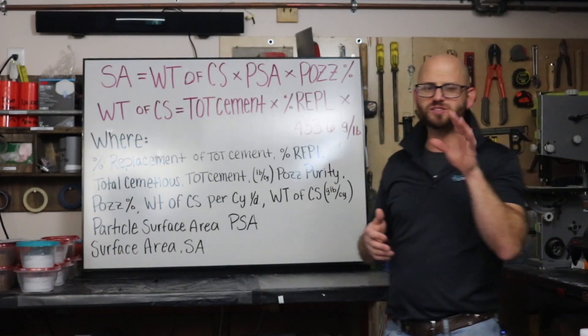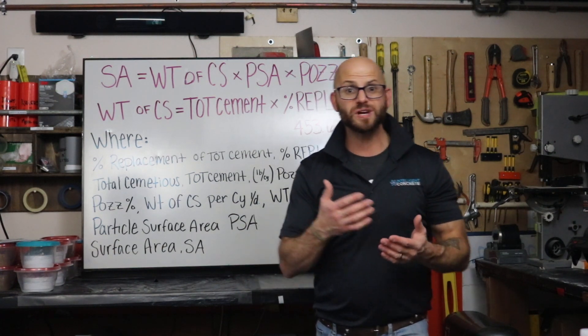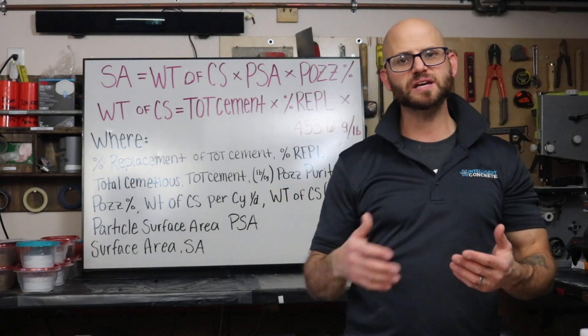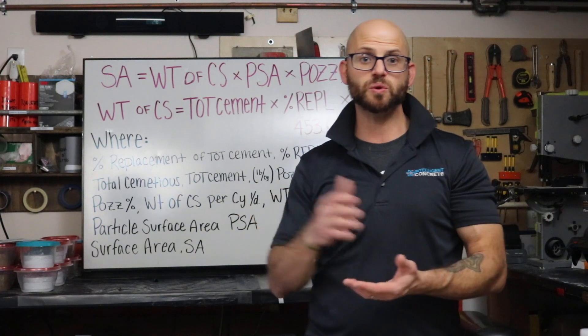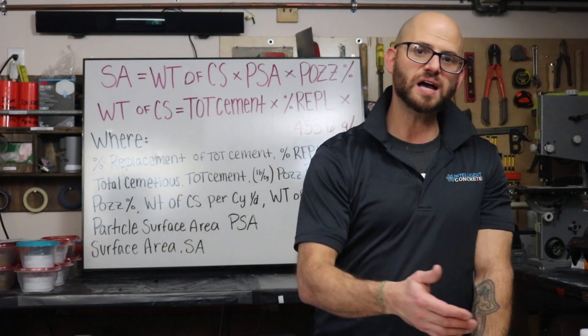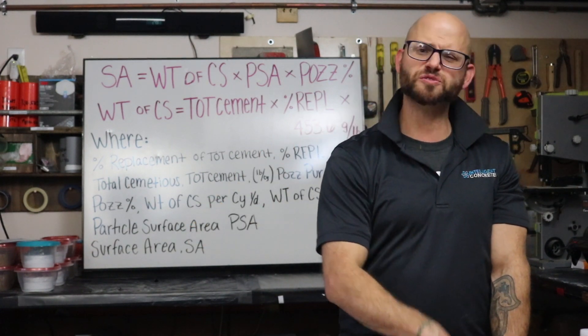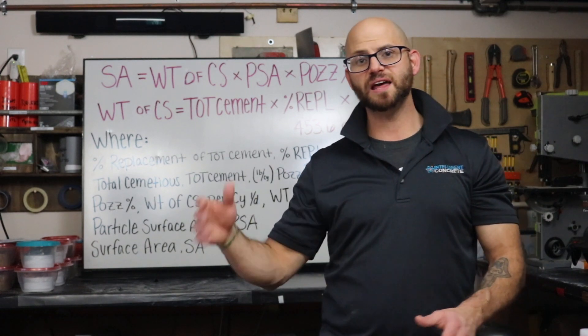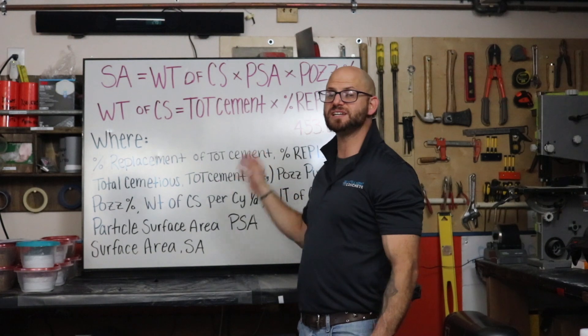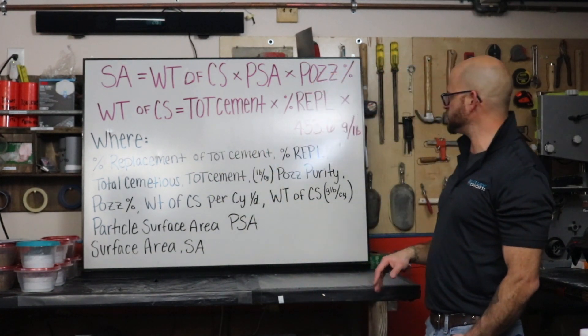Finally, multiplying by our percent pozzolanic purity gives the final value: meters squared per cubic yard — a somewhat unusual unit. We use this when back-calculating the amount of colloidal silica we want to use in comparison to, say, silica fume or Class F fly ash, where we can determine the silica surface area that those materials bring, and then determine how much colloidal silica we need to achieve that same surface area.